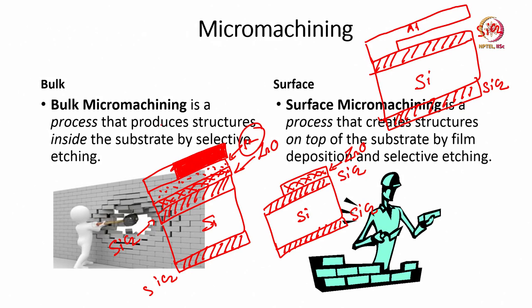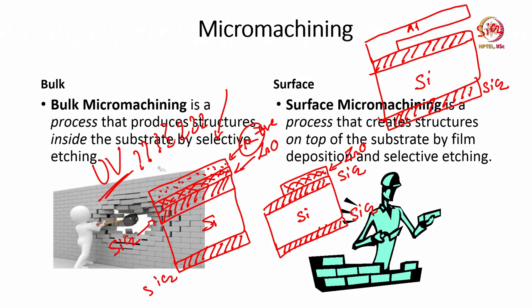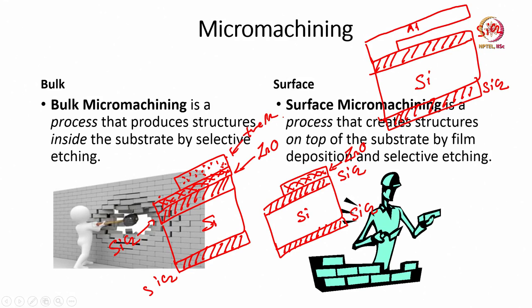When we expose through the mask using UV light, the unexposed region gets stronger and the exposed region gets weaker in positive photoresist. Remove the mask, develop the photoresist — it stays in the unexposed regions. Perform hard bake, then dip the wafer in zinc oxide etchant. The exposed ZnO is etched away, leaving a patterned ZnO structure on the oxidized silicon substrate.